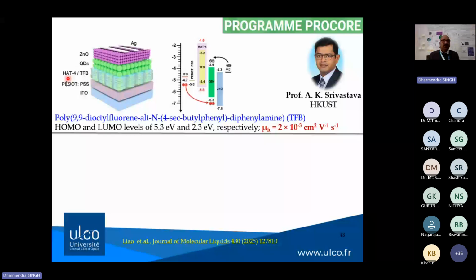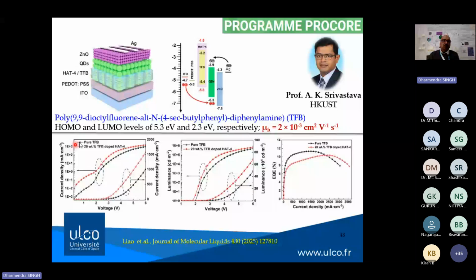When we mixed around 20% of the HAT4 with the TFB and measured the current density, we found that the current density had increased, because HAT4 is a photosensitive material. It generates photo carriers. This means that the increase in charge carrier density is associated with additional charge injection in the device, and that's why the current density of the LED device is increased. So we recently published this paper